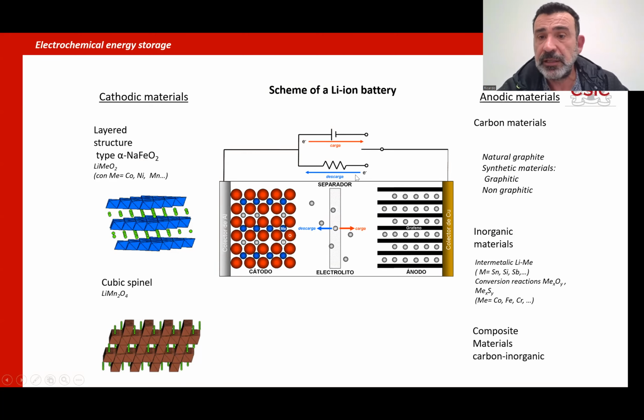And in the negative electrode, what you have is a carbon material. You have graphite as the anode material in all lithium-ion batteries that you find in the market. A huge amount of graphite is used for this application. And the reason, if you remember the layered structure of graphite, is that between the layers you can introduce the small lithium atom. Then you have an electrolyte, which is relevant, but not for this talk.